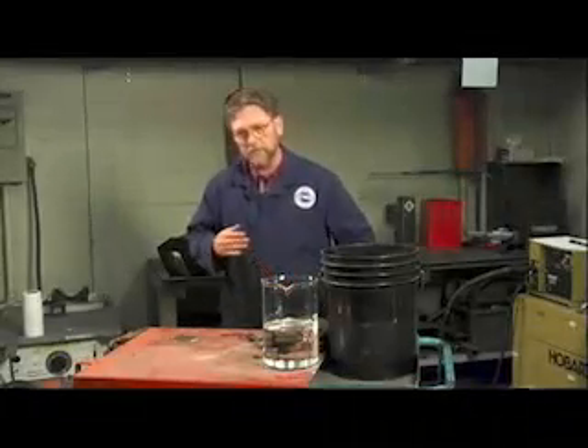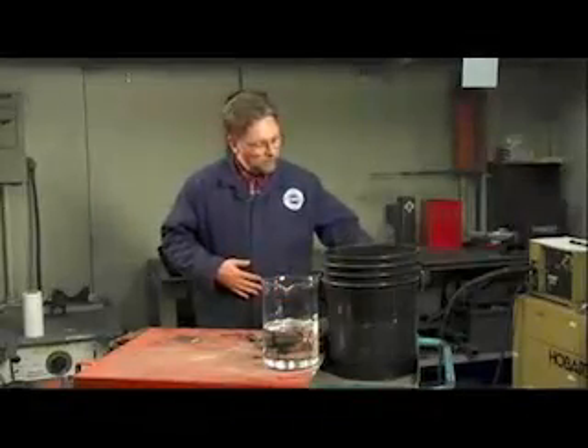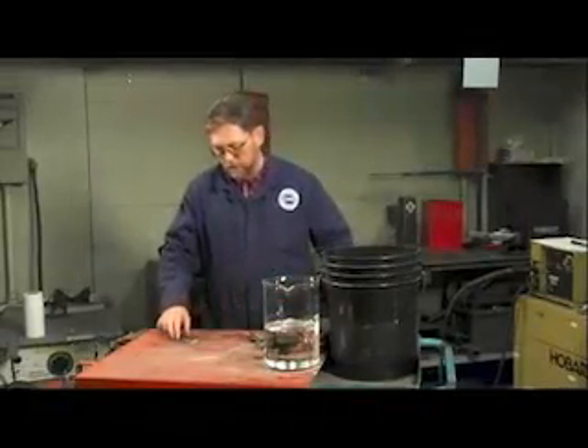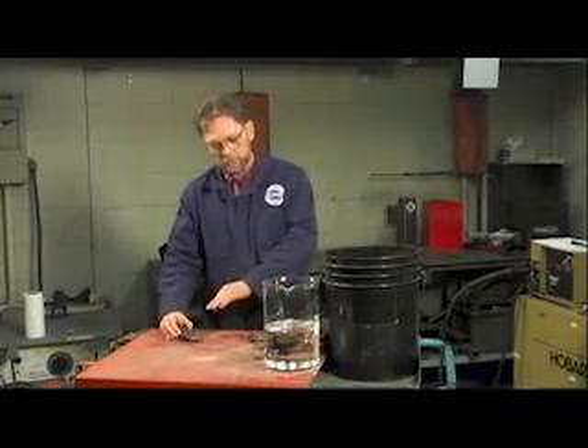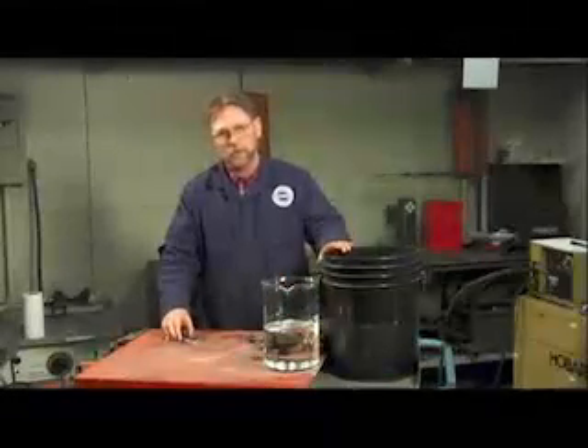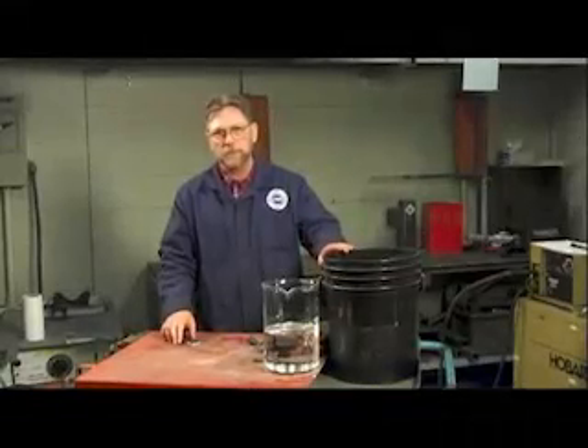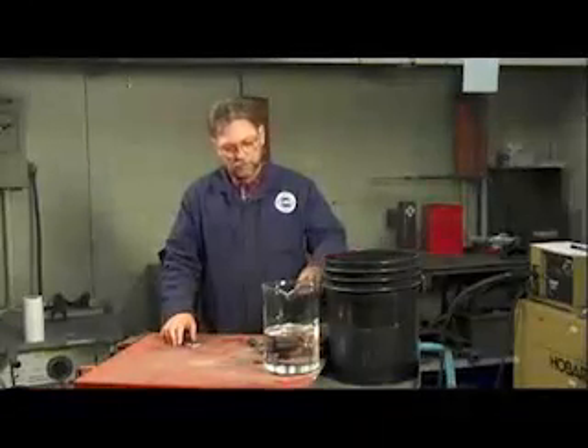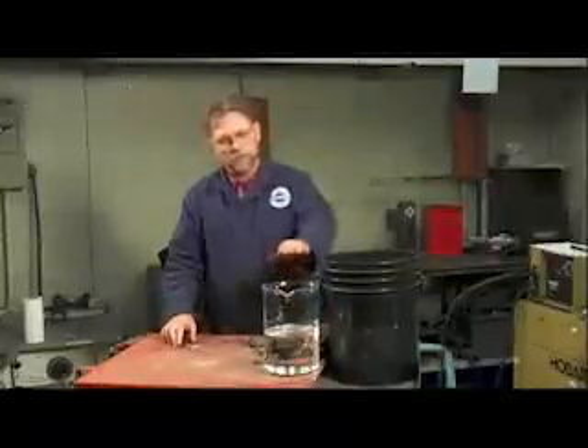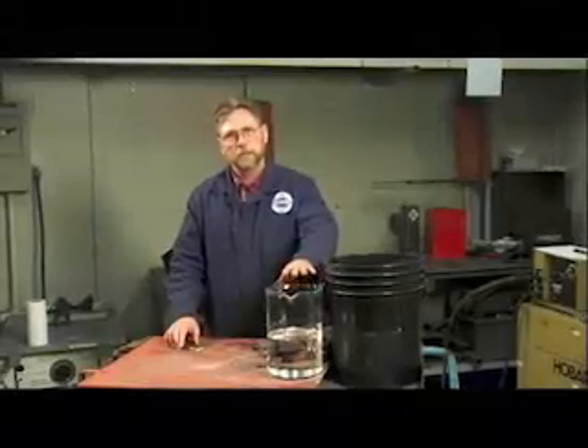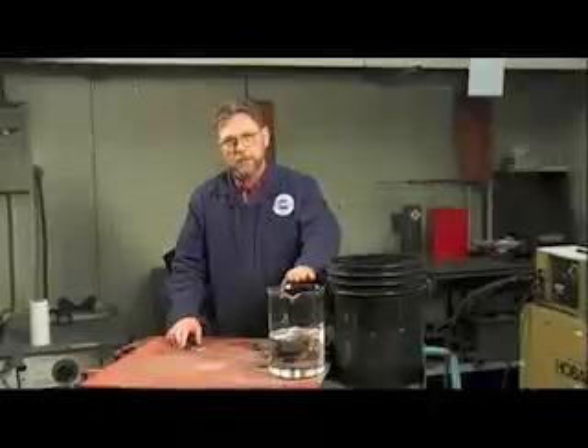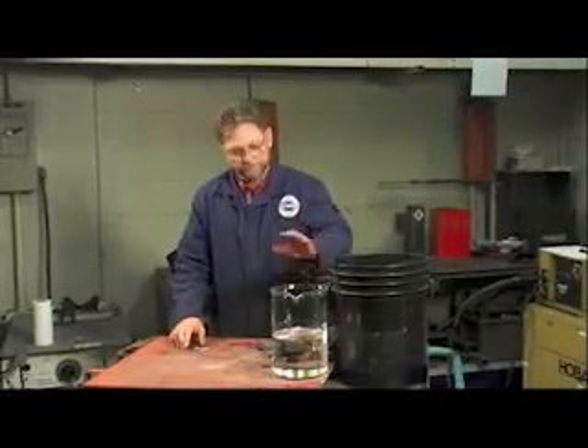So if we do the same demonstration again, using the gas metal arc process, I'm going to make a small bead on this piece of metal. I'm going to quench it into cold water to shrink the material down, and if there is any hydrogen in there, it will be trapped. And then I'm going to clean it off, dry it. I'll put it into this beaker of a clear light oil, and then you can see that there won't be any hydrogen bubbles coming out of it.